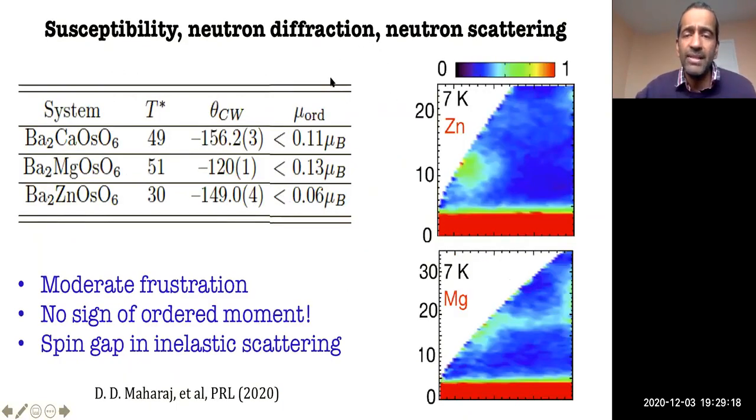So in more recent work, in which we were collaborating with the experimentalists, they went and did a very careful neutron diffraction study to look for the size of this moment. The only thing they were able to do is place bounds on it. It's consistent with the mu-SR experiments, but they have now explicitly gone and checked, and they find no detectable moment. The best bound here is on the scale of a 20th of a Bohr magneton.